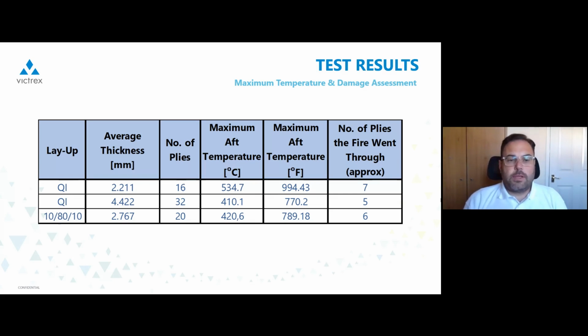So we had a typical quasi-isotropic laminate of 16 plies that was around 2.2 millimeters thick. And what I have said here is the fire temperature is 1100 degrees C or 2000 Fahrenheit. So this is what you have at the front face. You start with 2000 Fahrenheit or 1100 degrees C, and at the back of a panel, which is 16 plies, just 2.2 millimeters thick, the maximum recorded temperature was 534.7 degrees C or 994 F. So just to put this in perspective, you start with something which is 2000 Fahrenheit, and after 2.2 millimeters of material, you go down to almost 1000. So you have a 50% reduction of the temperature. That was for the thinnest panel of 16 plies.